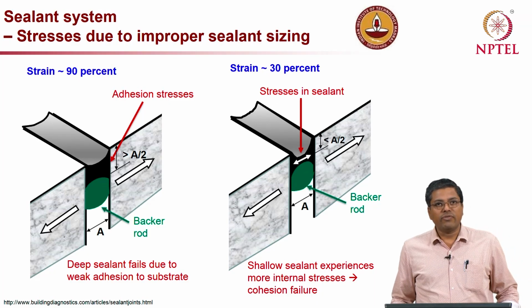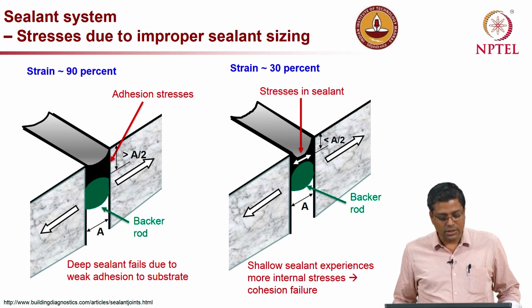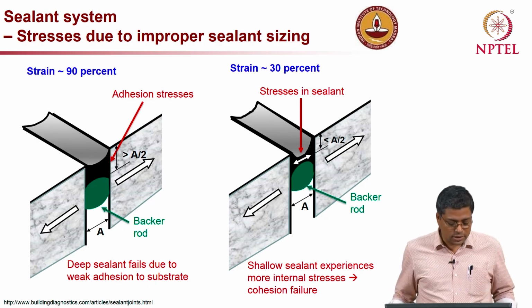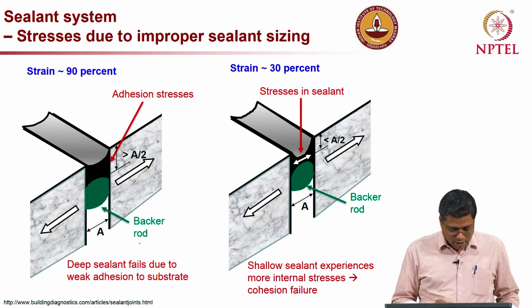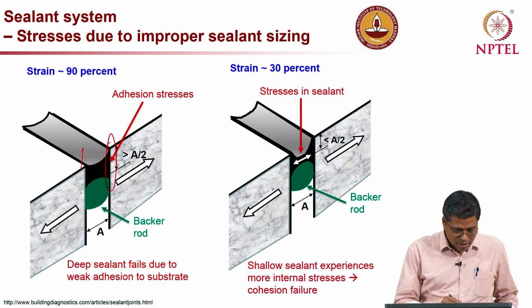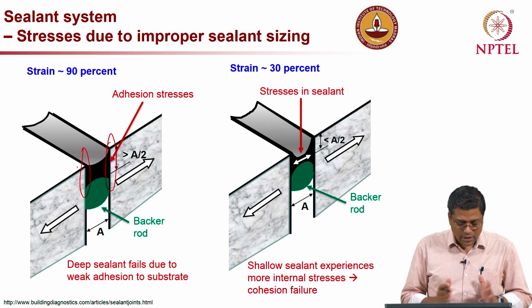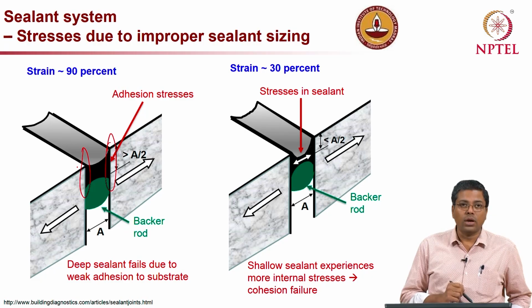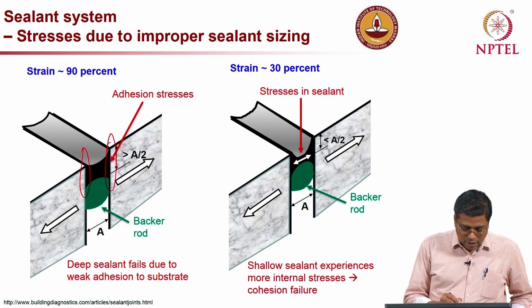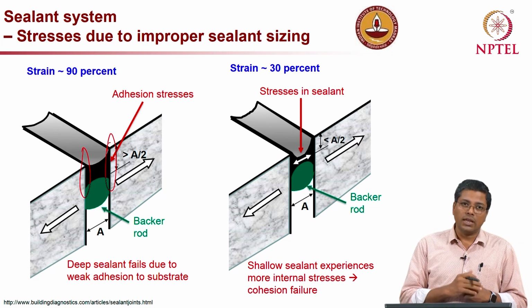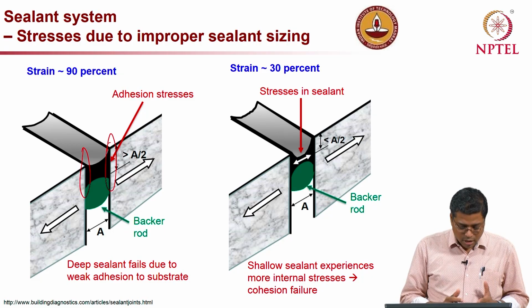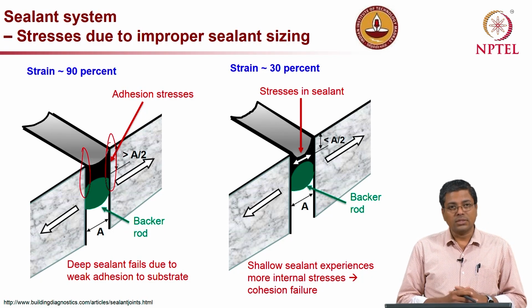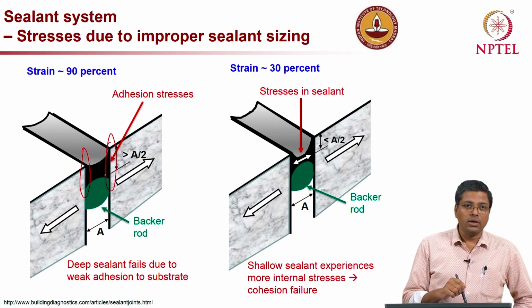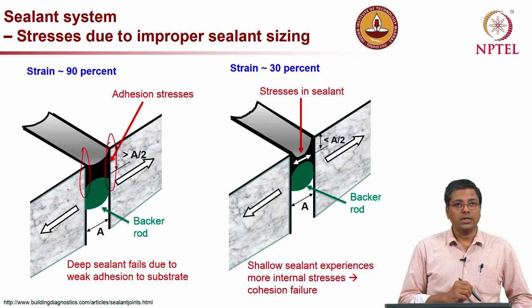Now, let us look at what are the different stresses that these sealants go through depending on their positioning and size, depending on the positioning of the backer rod, etc. The one on the left side, what you see here, is a deep sealant that fails due to weak adhesion to the substrate, on the vertical faces which you see in the picture. The green one is the backer rod, and in such cases, when the thickness of the sealant is relatively more than half of the diameter of the backer rod, the chances are high that it will fail because of adhesion failure between the concrete and the sealant.